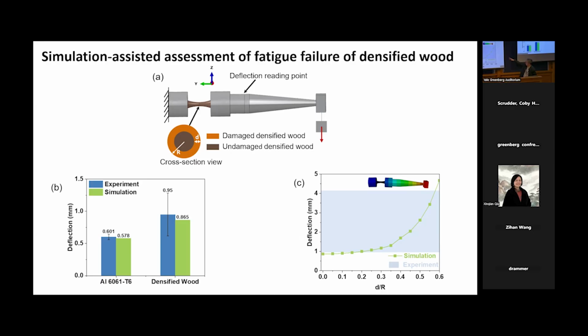And then if you have the fatigue damage, as we show here, when the x-axis value increases, it means more damage to the cross-section, then the deflection increases because it becomes weaker, right? So the simulation is the red, the green line, and it captures well the blue shade here, which is the experimental measurement of all the samples we tested. So this means that if you can run the simulation and also test the deflection of the unfatigued superwood sample, we can estimate how much it is damaged along the cross section without cutting it.